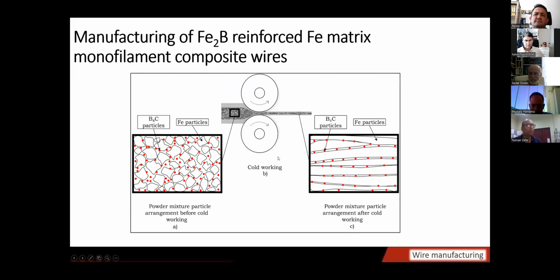What we are expecting from the materials is that this is a powder mixture in the non-deformed state, and this is the powder mixture arrangement after the deformation. Before, B4C particles being ceramic and hard are not going to experience any deformation, but the iron particles, the white ones, are going to be elongated after the cold rolling. This is something we are anticipating right now. Of course, it is expected.